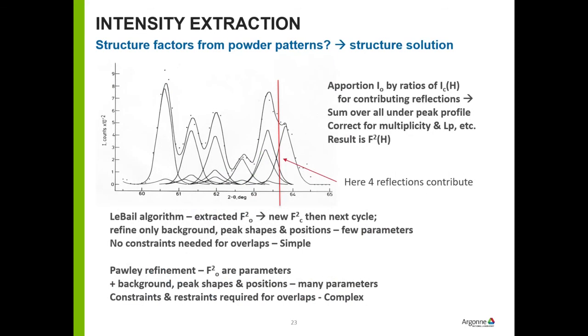Okay, last topic, and that is how do you extract intensities from a powder diffraction pattern? Well, you have to have a fit first by a Rietveld method or by one of the other methods, which is the Le Bail algorithm or by Pawley. For the Pawley method, it's fairly obvious. You simply make all the structure factors variables in the refinement.